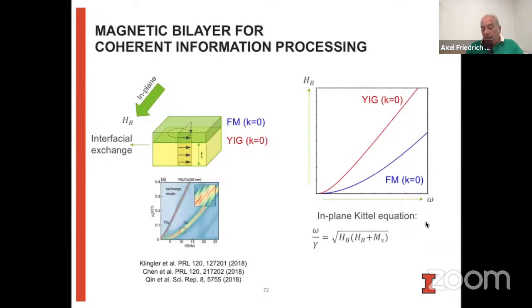But one of the issues, and you see this already very nicely in this diagram, is that unless you have some additional anisotropies, if you have two different magnetic systems, then they really only cross over close to k equals zero. Because the Kittel equation is given by the saturation magnetization and these effective fields. So if you don't have any other anisotropies here, it goes as the square root of the magnetization. And if the magnetization is much higher for the cobalt, it always lies underneath where the yttrium iron garnet mode is.